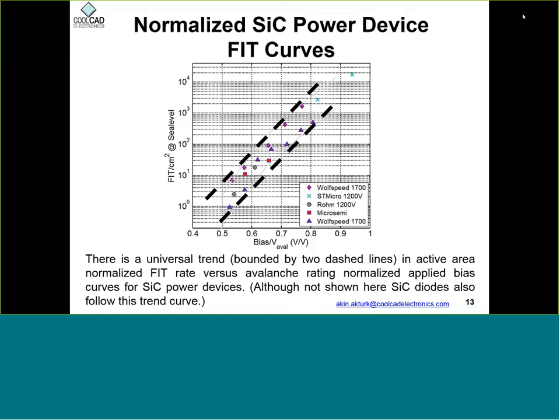Okay, thank you. How does the rate of these neutron-induced failures compare to other potential failure mechanisms in silicon carbide devices, for example, due to material defects or other phenomena? There is not much direct correlation. When neutrons knock atoms off their sites, that doesn't always mean the device will be more leaky after that. The neutrons are kind of funny. Sometimes by irradiating a device with lots of neutrons, you may see the device characteristics improve. That's kind of counterintuitive. So you can go either way. It's not always the case that neutron radiation gives you worse effects.